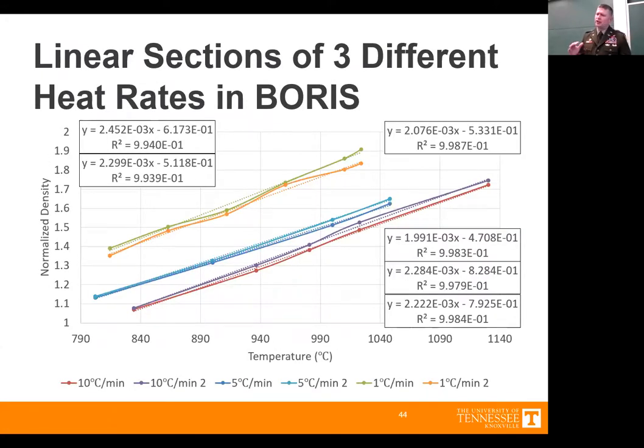Specifically, when I zoomed in and looked at where those sintering rates were linear, I saw that, again, that fit of the data, that linear regression, was almost identical for multiple different heat rates. So you can see here, these are different trials of the same heat rate, and then 3 different heat rates. So a total of 6 different trials. Remarkably similar slopes of those lines of best fit. R squared values almost 1 in every case. So the data is pretty good.